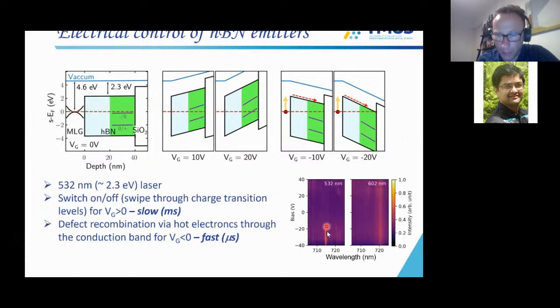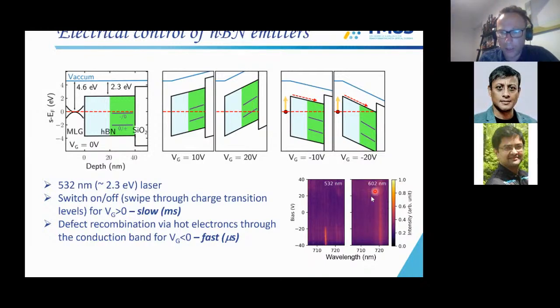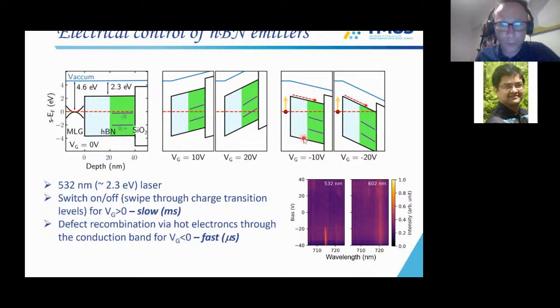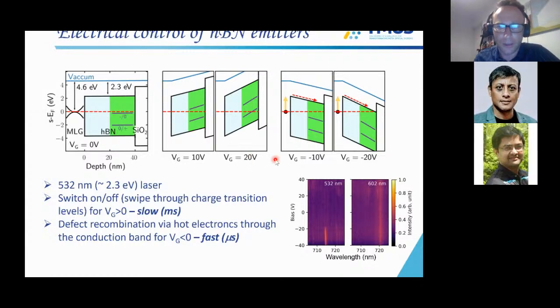So here is an emitter, for example, emitting at 710 nanometers that is on at very high biases. And as we change the excitation laser to 600 nanometers, exactly at the same confocal spot, looking exactly at the same system, we actually see absolutely nothing. And so this is just the Raman line of the 600 nanometer excitation. So this basically proves that there is a different excitation mechanism from these defects, and trying to understand these dynamics a bit better.